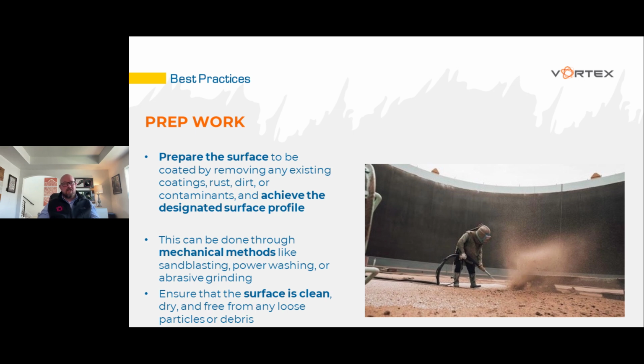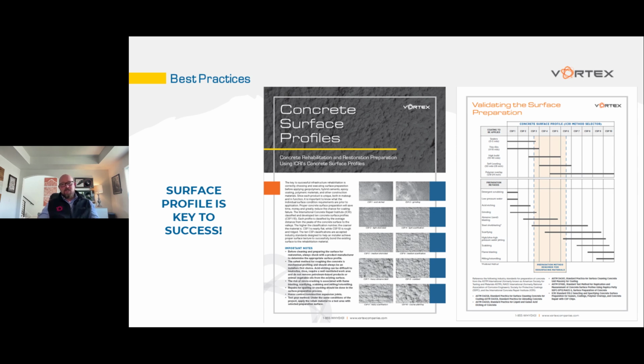A lot of the time we have to do this not just using high pressure water, but sometimes we need to open up a profile using sandblasting or multiple methods: power washing, abrasive grinding, sandblasting, dry ice blasting, you name it. But once we've got loose debris off and the surface profiled correctly, and then cleaned correctly, it's in alignment to accept the next material, which in this case is a protective coating like an epoxy or polymeric material. We've worked really hard to create and define those surface profiles along with the standards that already exist. When we go through training with our certified applicators or even our internal crews, surface profile and prep is a majority of what we're going over before we install that material.